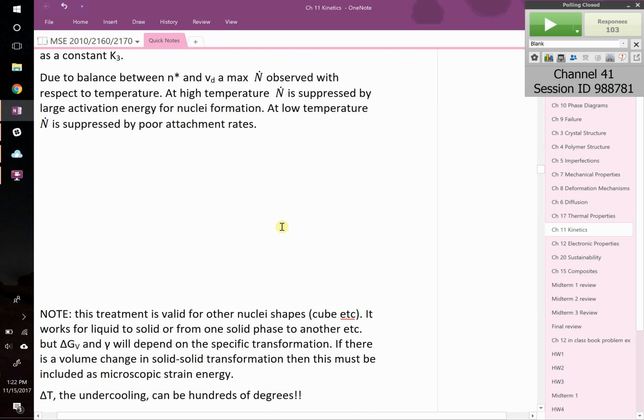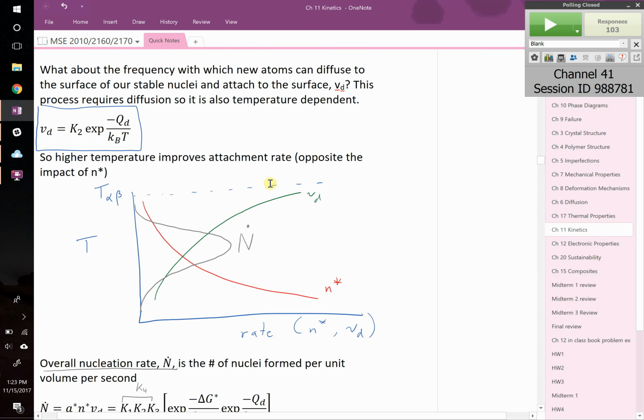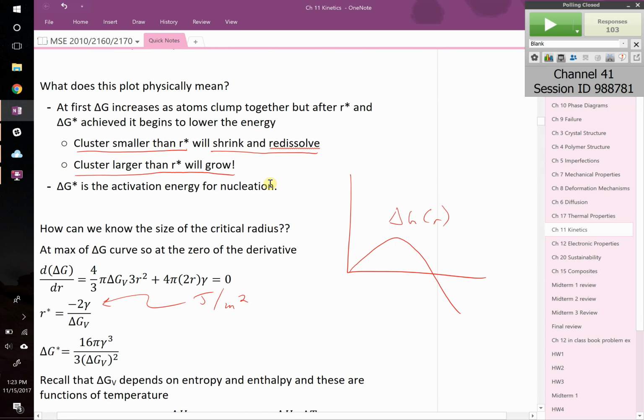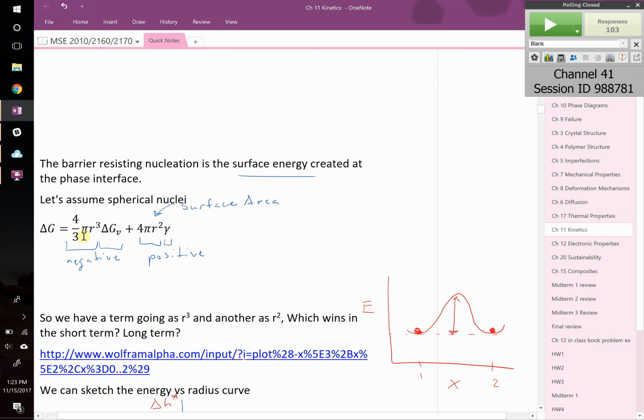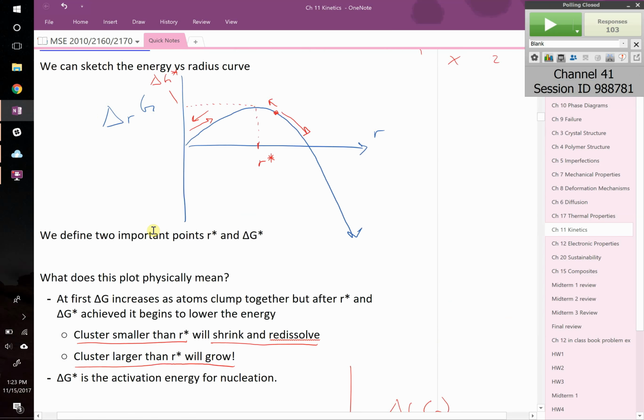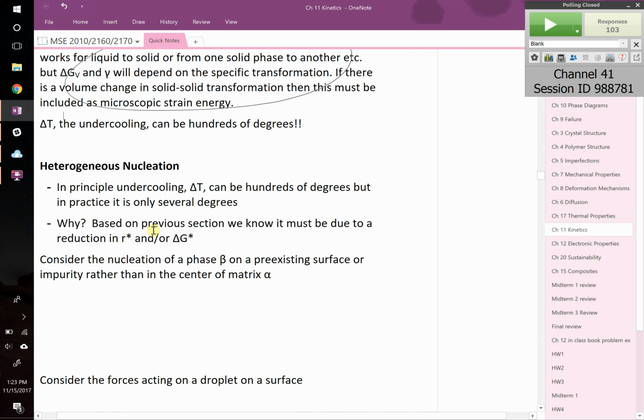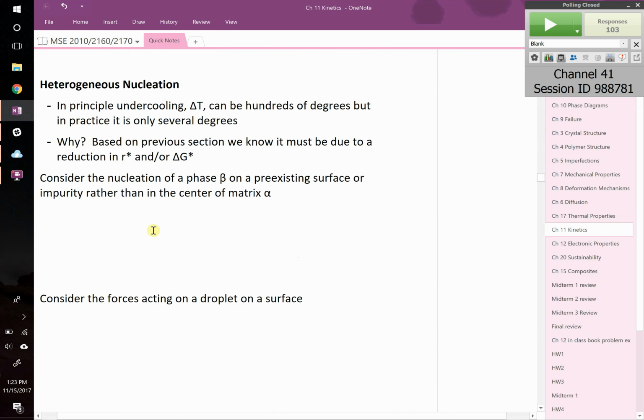I'll just remind you that everything we've done up till now has been for spherical, right? If you do any other shape that isn't spherical, if your crystal structure grows big cubic crystals, for example, or any other shape, you have to redo the math, but it's not so bad because the only place that comes into play is in the volume and the surface area equation. So if you go back up here, you would modify this 4/3 pi r cubed, that's the volume of a sphere, and you'd modify the 4 pi r squared, that's the surface area of a sphere. Instead of that, you do whatever other shape it's crystallizing in. Okay. That's homogeneous nucleation. Let's pivot now and talk about heterogeneous nucleation.